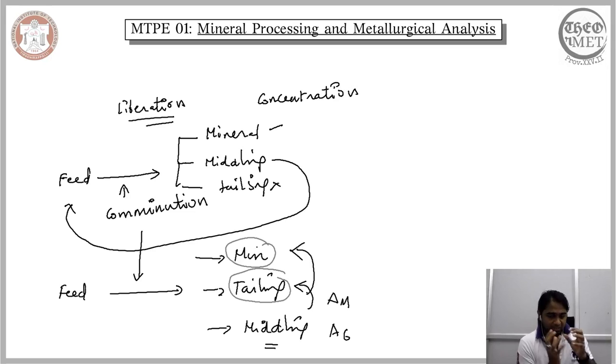We can categorize that portion of the middlings as free mineral particles. Similarly, since some contain a greater or equal amount of the gangue mineral, we can categorize a specific portion of the middlings as tailings, and we can subsequently treat these portions with the acceptable level of minerals and acceptable level of gangue as we would treat the minerals and tailings respectively. The rest of the middlings we can send back, or subject to the second degree comminution.